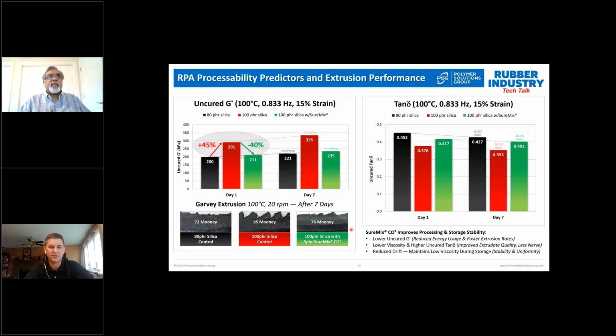So you can see if you look at uncured G prime, and we use uncured G prime on RPA, we usually talk in those terms as opposed to Mooney viscosity, simply because the RPA is very sensitive and we can see changes that sometimes won't show up on Mooney viscosity alone. But you can see the increase in the uncured G prime, increase in the viscosity going from 80 to 100 parts of silica in the black to the red bars on the top left here. So it's a 45% increase in the viscosity of the compound. Using SureMix in that 100 part compound, we're able to reduce that viscosity by 40%, bringing it down very close to the viscosity of the 80 part silica compound.